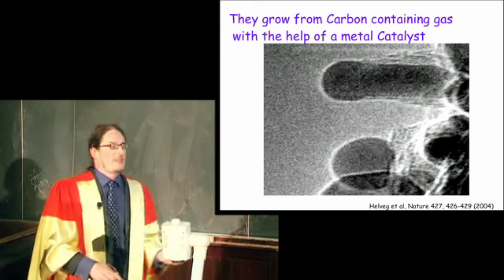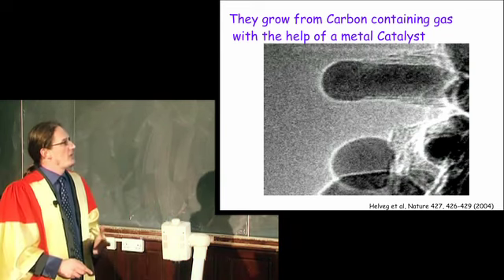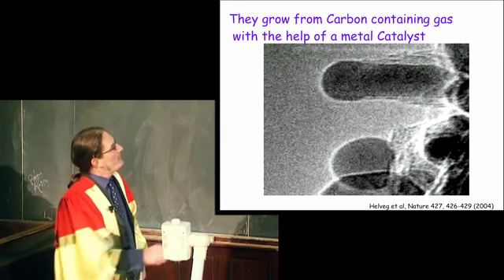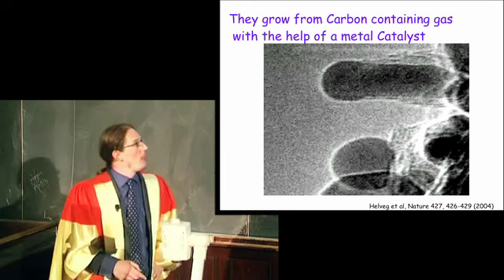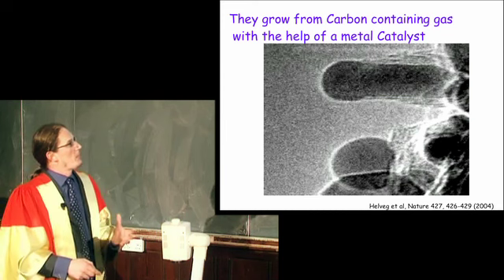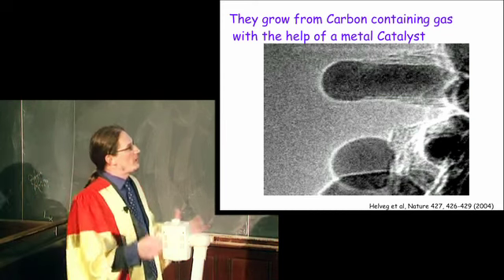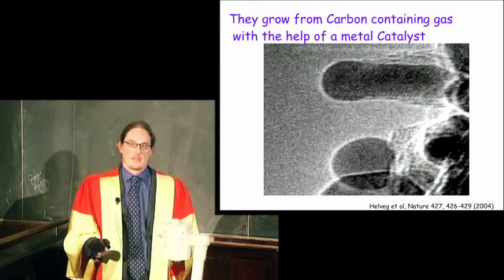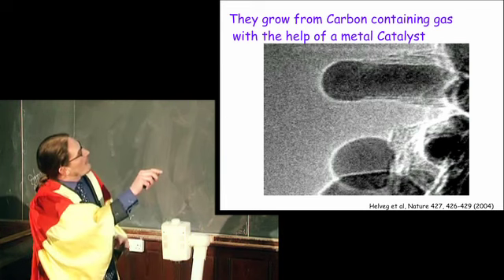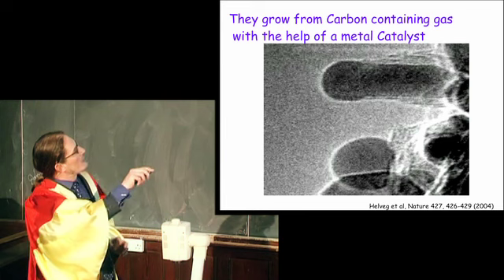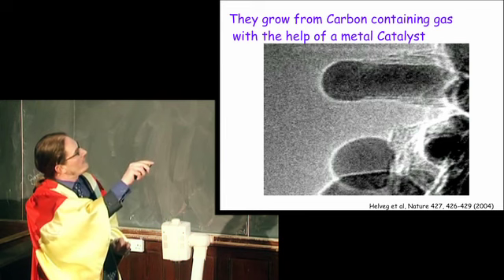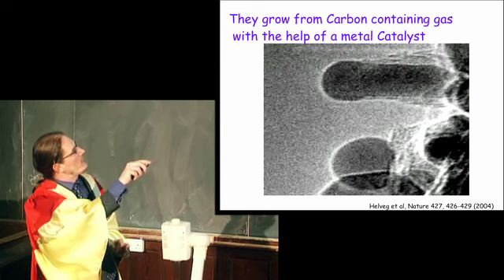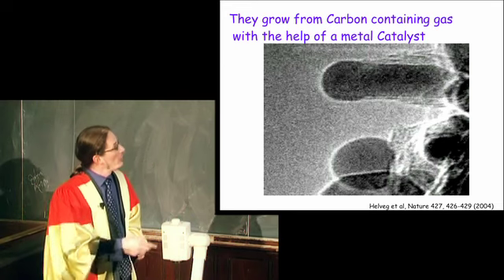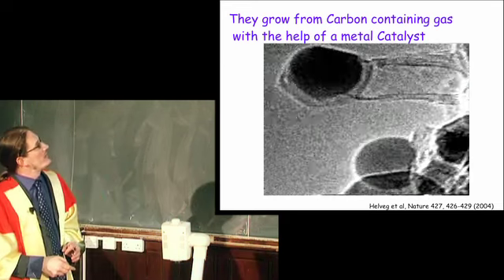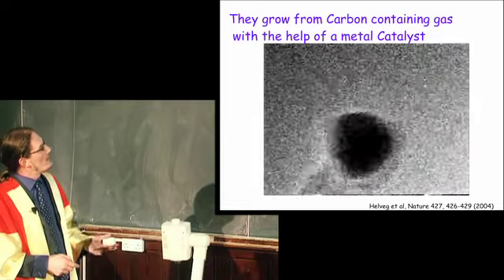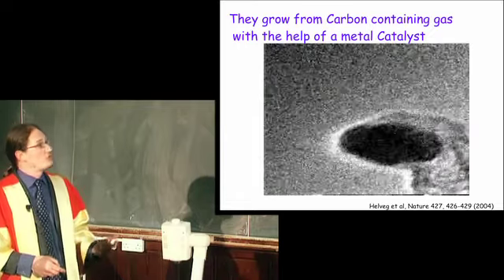Well, at the start, they were made sort of by accident, but very quickly people learned how to do it. And this is a movie taken in an electron microscope showing the growth of carbon fibres. Now, these are not carbon nanotubes. They're much bigger than carbon nanotubes, but the growth mechanism is the same. Basically, you have a piece of metal catalyst, and you have a very, very hot gas. The gas goes into the metal catalyst and is pushed out the side to form a tube. So just to show you, you can't see the gas going in, obviously, but you can see the stuff coming out in a tubular form.